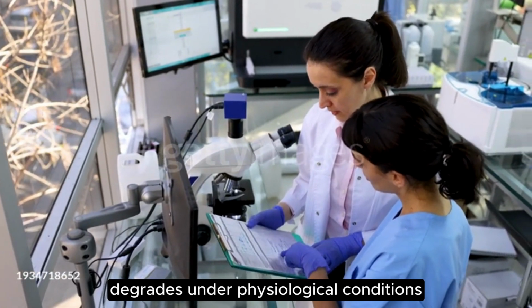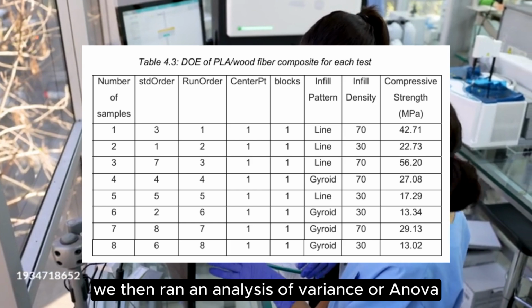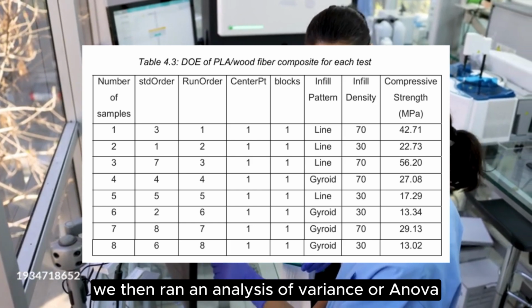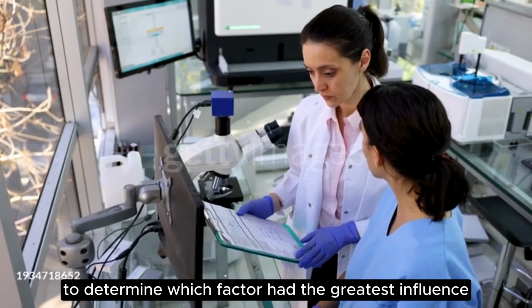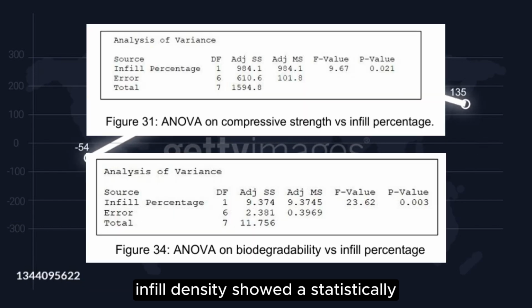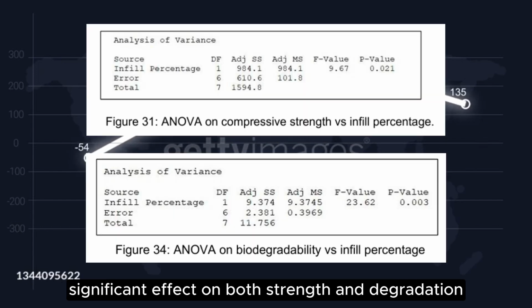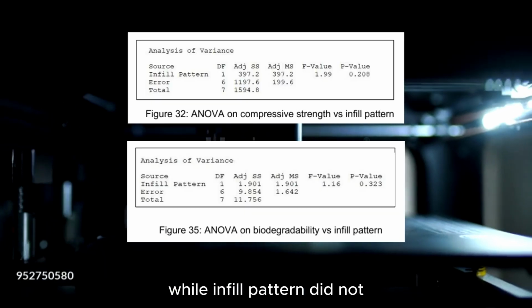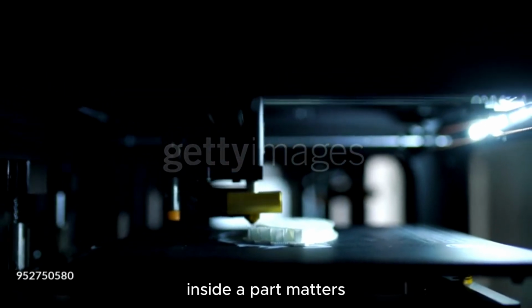degrades under physiological conditions. We then ran an analysis of variance, or ANOVA, to determine which factor had the greatest influence. Infill density showed a statistically significant effect on both strength and degradation, while infill pattern did not. In other words, the amount of material printed inside a part matters considerably more than the shape of that material.